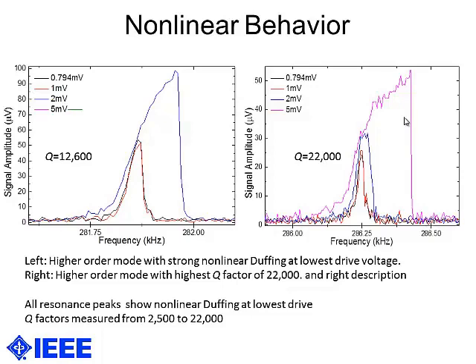On the right, we show the highest quality Q factor of 22,000, and it also shows a very strong nonlinearity. All of the peaks showed a strong nonlinearity at the lowest drive voltages that we could measure, and the Q factors again ranged from 2,500 to 22,000.